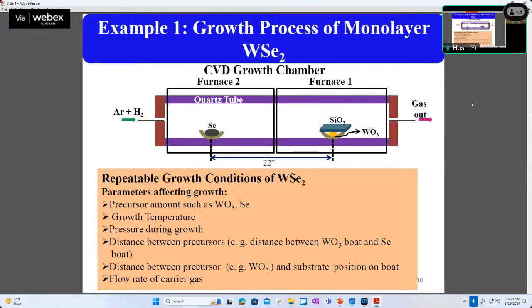This is one 2D material, and typically for this growth, my group uses a CVD system, and this is a 2 furnace system. You can see here in the schematic the furnace 1 and 2. It is shown in the schematic.